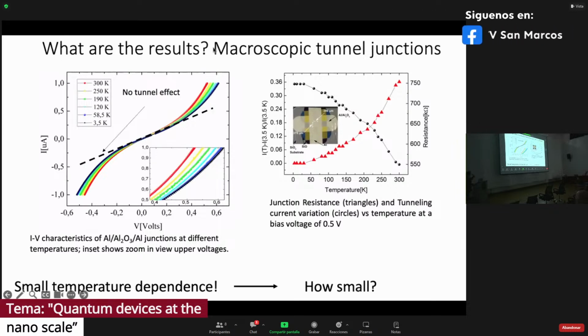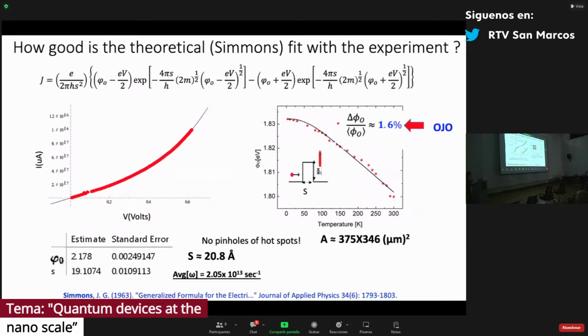So here on the right, you have the results on resistance versus temperature. You have the fit of the theory with the experiment. Here you have the famous Simmons model, and how it fits the theory with the experimental results. The fitting is very good. And the important part of this is that you get the barrier width, so this is the tunnel. You get the barrier width, or how thick this barrier is, and the barrier height. That's the important result that you will get from this data.